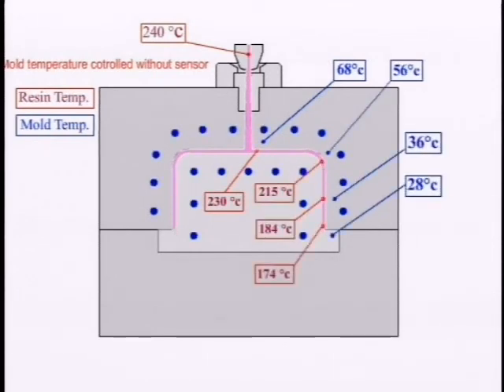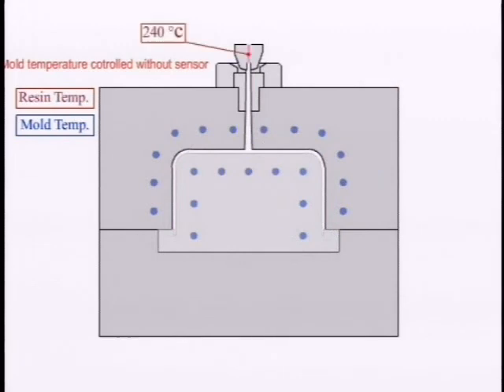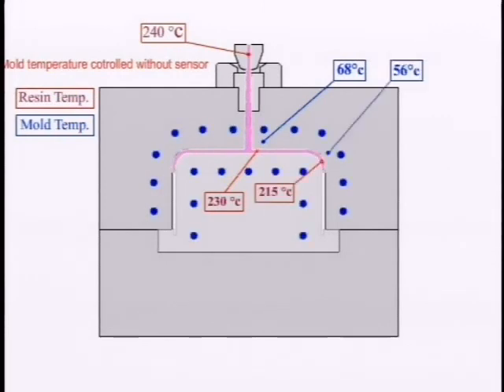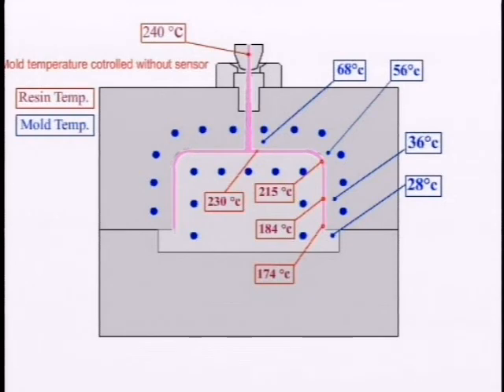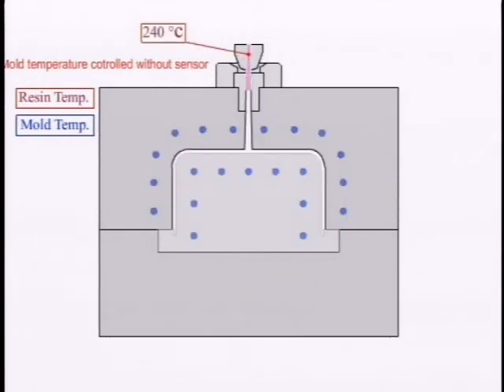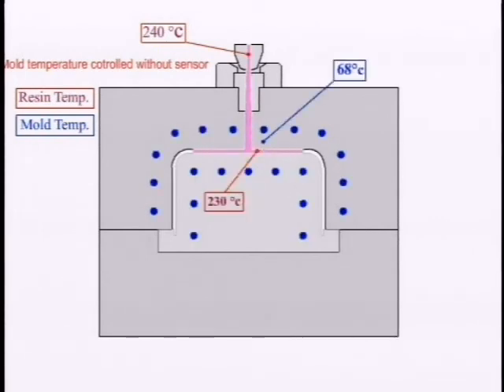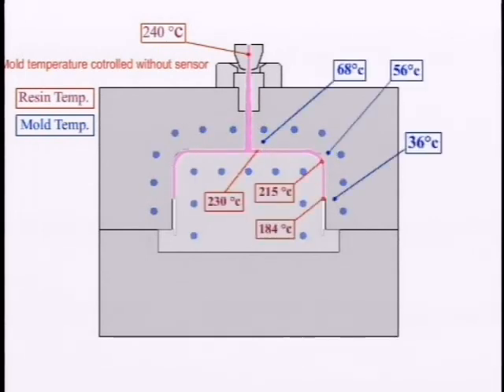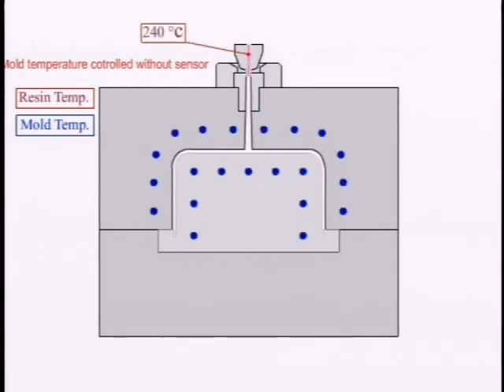In the early stage, inferior molding products occurred in large quantities, as much as 80 to 120 pieces. Lots of heat capacity was transmitted to the gate, and the mold temperature showed 68 degrees. And it took us a lot of time to cool the filled resin, so the production cycle time was 90 seconds, which meant low productivity. Therefore, due to high inferiority rate and low productivity, the production cost was so high.